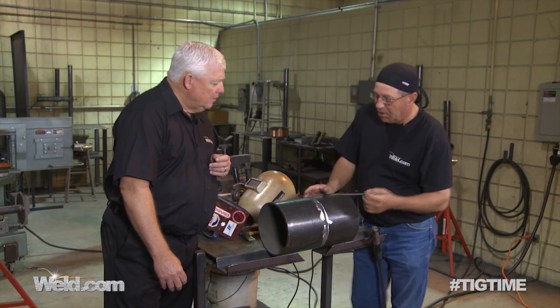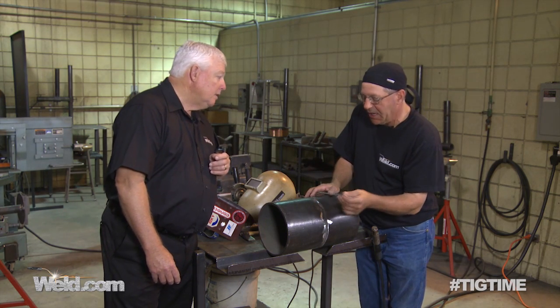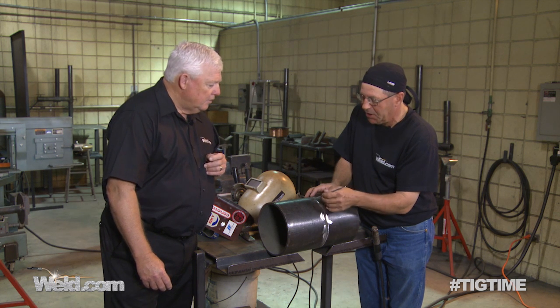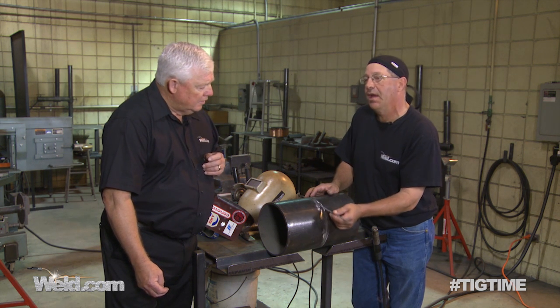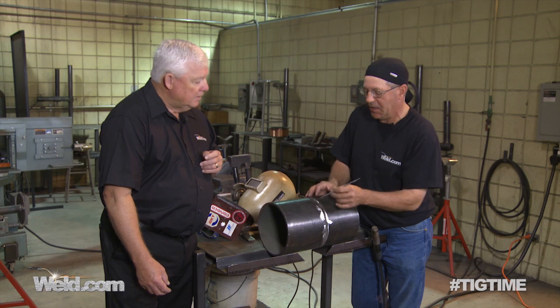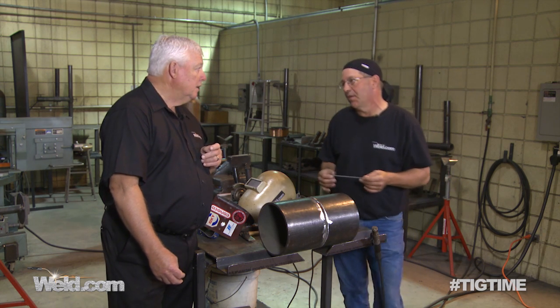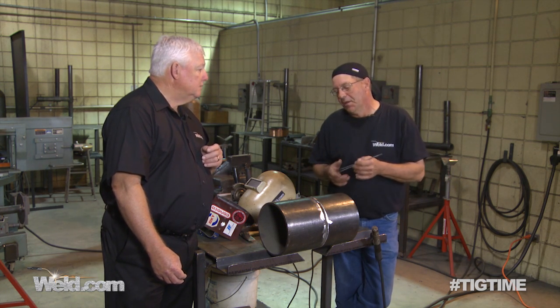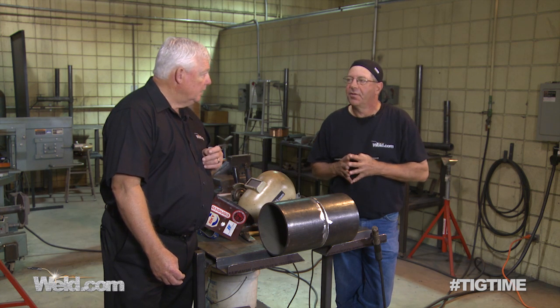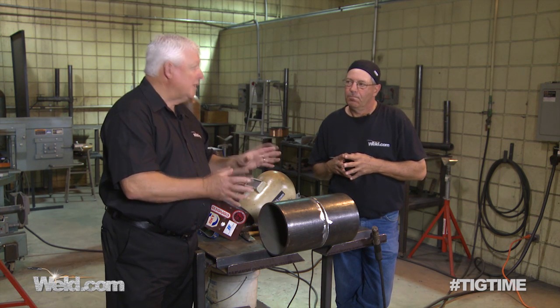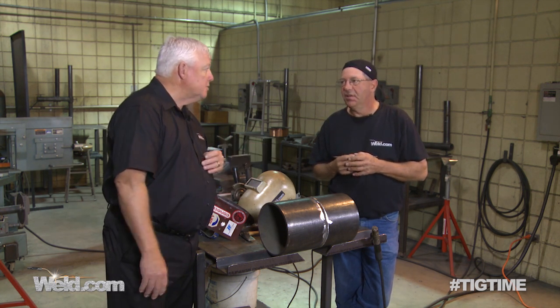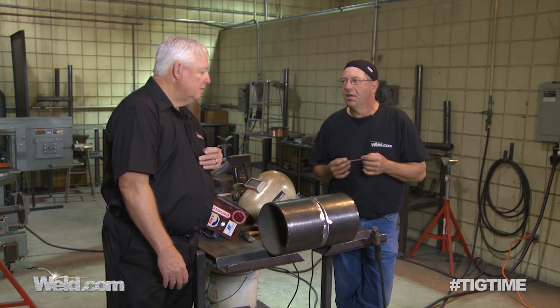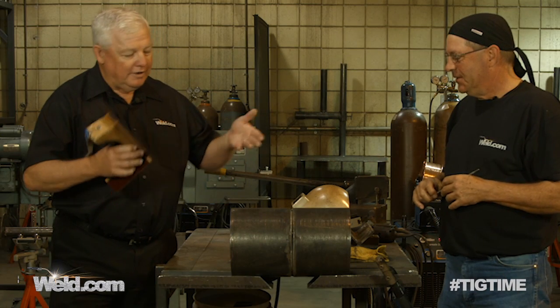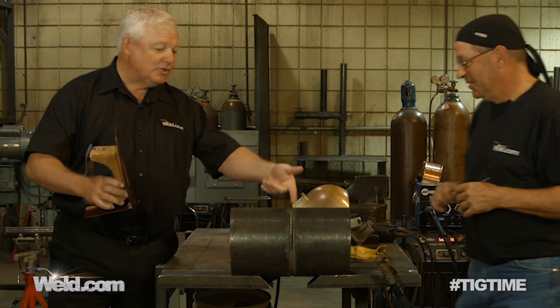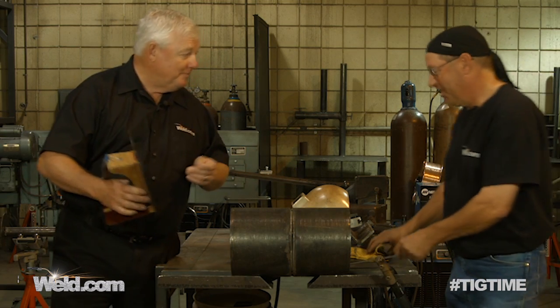On this particular wall thickness, I will run an 1/8-inch root. I will do a 1/8-inch fill or a hot pass. Little technique on that, and I'll probably switch to a 5/32, next size bigger rod. And I'll do a fill and a cap with 5/32. Okay, so all the rod's going to be the same type of rod, just different diameters? E6010, just different diameter. Well, okay, let's get our gear on, and I'd like to watch you do this, because I've never done this type of test before. Let's go. Let's do it.